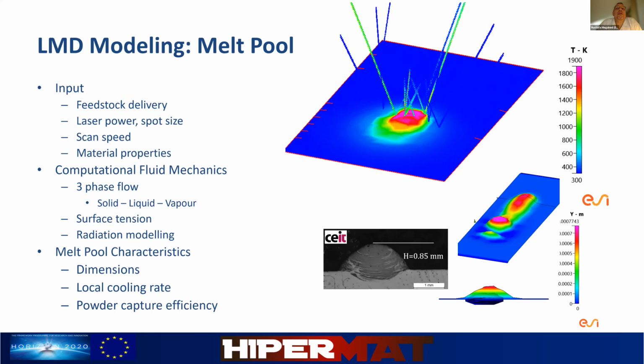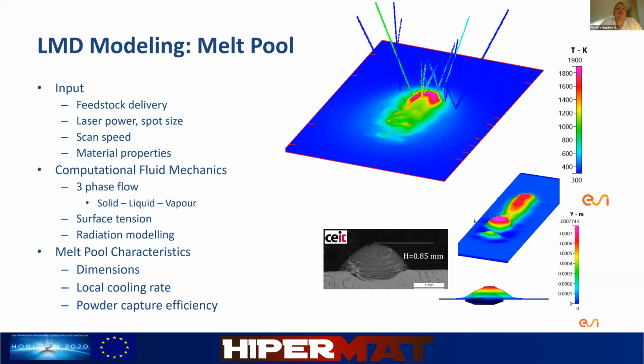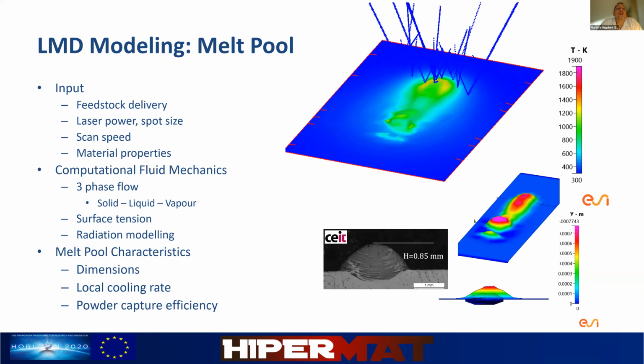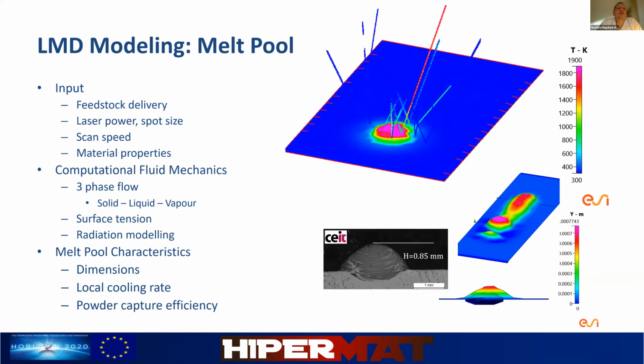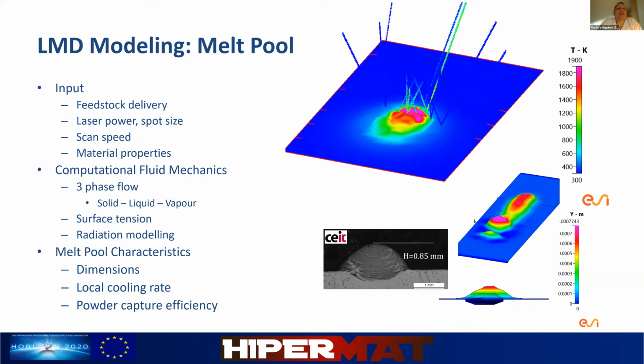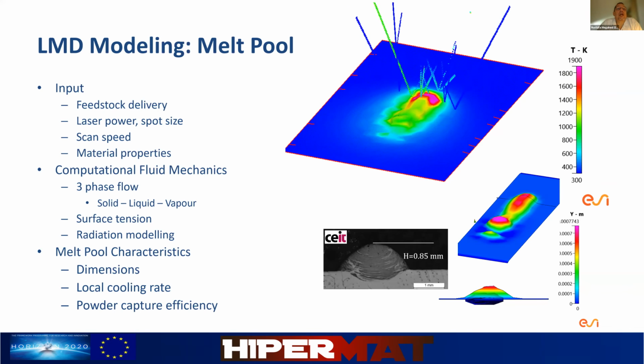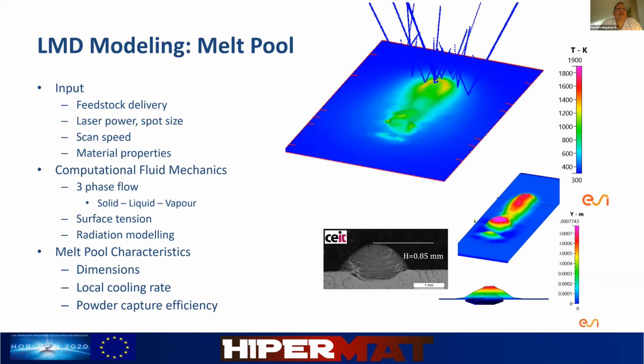Okay, so now we have the feedstock delivery. We know how the particles are flying towards the point of deposition. We also have parameters, including laser power and the spot size. We have the scan speed, how fast the nozzle is moving on the substrate, and we have the material properties. We know that we are depositing, in this case, Haynes 230 on a steel. So the material properties of both substrate and the deposited material are known to the model.